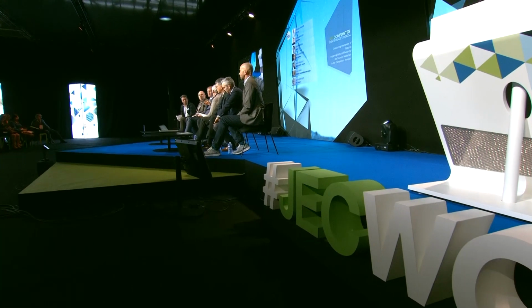And did you deliberately change something in the chemistry and the molecular structure of your thermoplastic, of your PP, or is it just by coincidence that it happened? So I'd say what we have is not really PP, but it is a bio-based resin belonging to the polyester family, and we specifically designed this resin towards binding to natural fibers. It's a PLA type resin? Yes, it's a PLA type, but a modified PLA resin with the affinity to bond covalently to natural fibers, really giving the strong interface and therefore a large improvement in the mechanical properties of the final composite part compared to the traditional inert thermoplastic polymers.